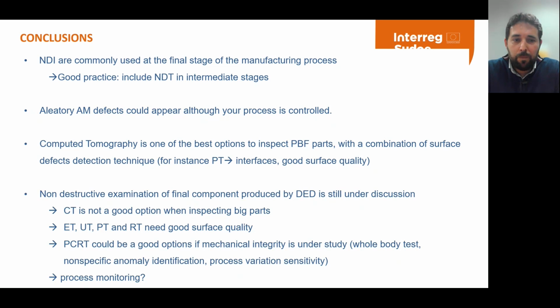Computed tomography is one of the best options in PBF parts, with a combination of surface defect detection techniques such as penetrant testing, for instance, but take into account that you need a good surface quality, for example, in interfaces that are normally machined.